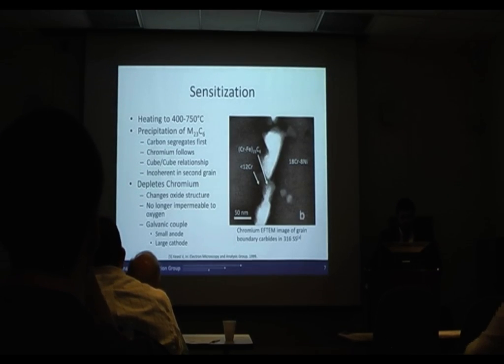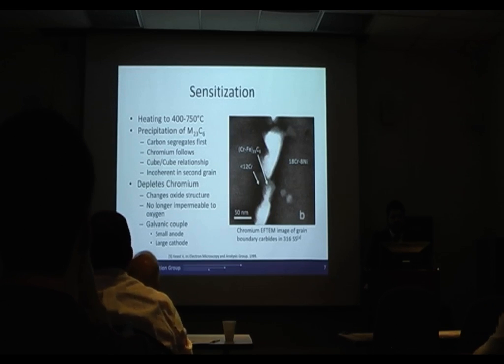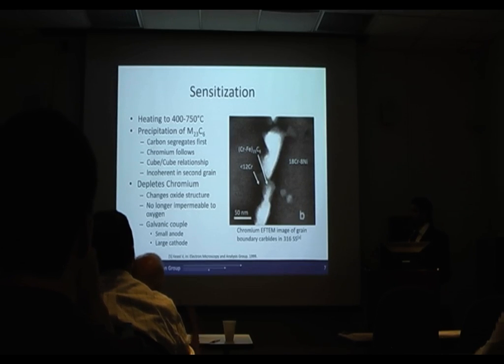So the problem with this stainless steel is that when it's heated into the 400 to 750 Celsius range, you get precipitation of M23C6 carbides. First you get the interstitial segregation, primarily carbon, to the grain boundaries. The chromium follows it, and you end up with these carbides precipitating there, which is shown in an energy filtered TEM image on the right. So in this particular image, since it's energy filtered, the brighter it is, the more chromium it has. So, Chad, this is slide 7.